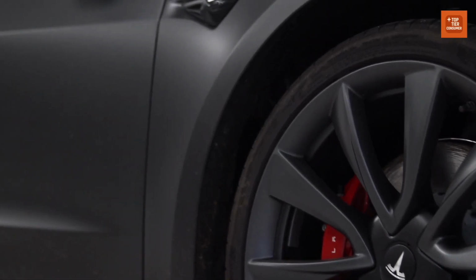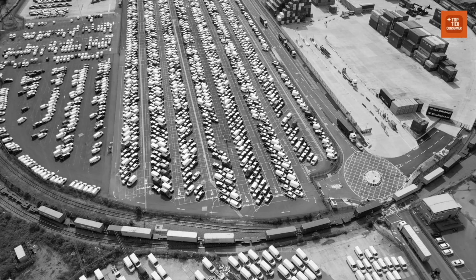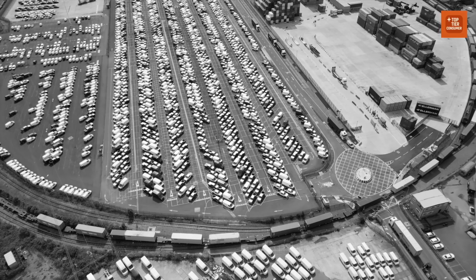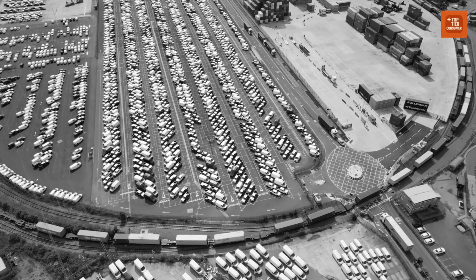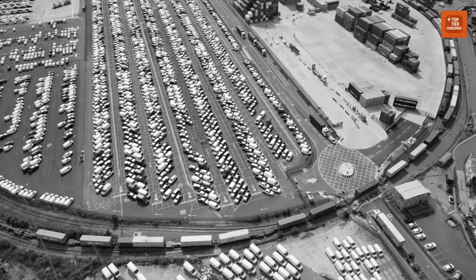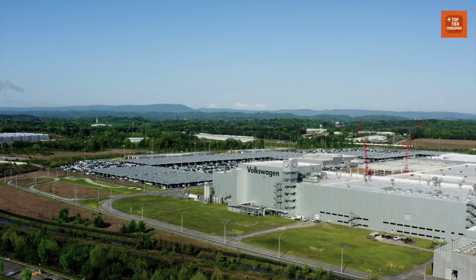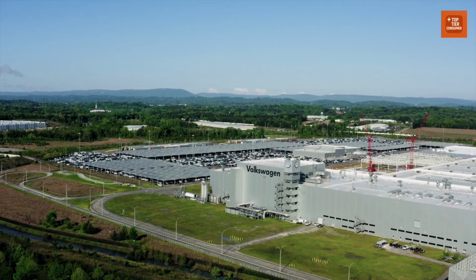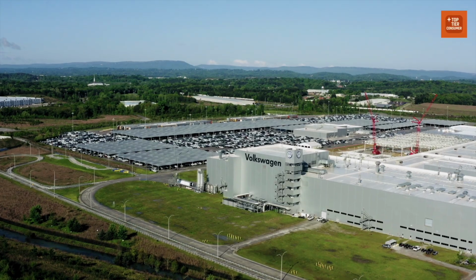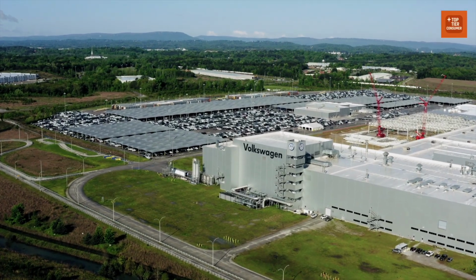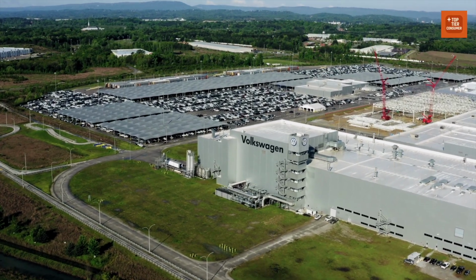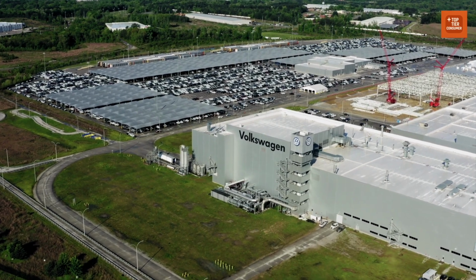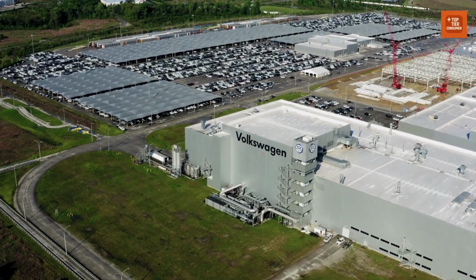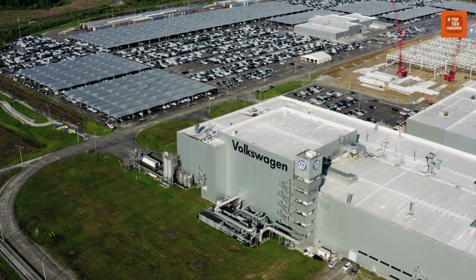QuantumScape, for example, has shared targets and early data for a cell architecture designed around a ceramic separator and a lithium metal anode, highlighting sub-15-minute fast charging from 10 to 80% and pack-level energy densities that push well beyond today's mainstream lithium-ion. The caveat is scale. Getting that performance from small test cells to large automotive-grade multi-layer cells at high volume is the mountain to climb.